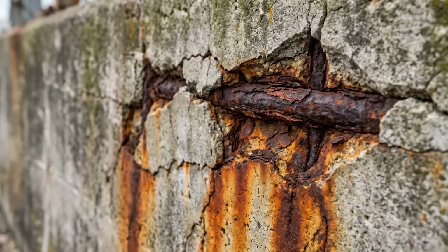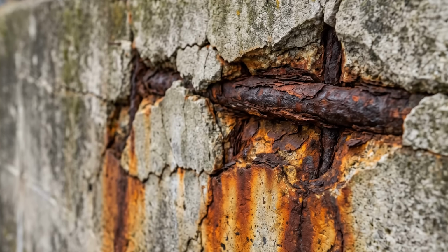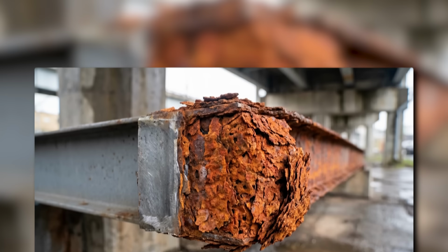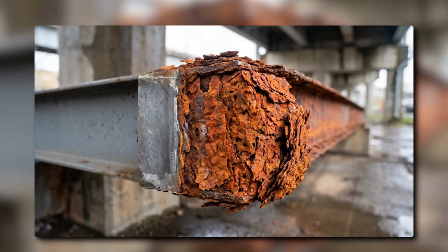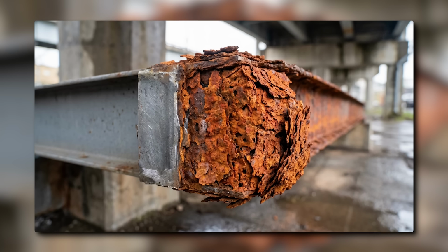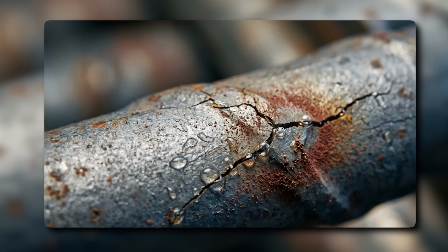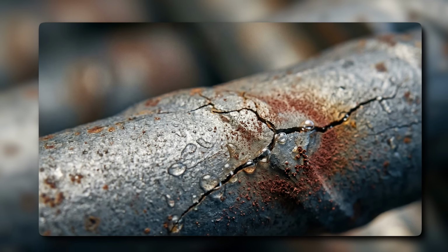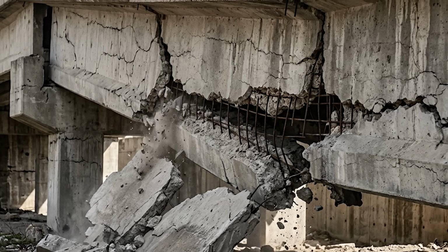Steel rebar has one fatal property: it rusts. The rust occupies up to 7 times the volume of the original steel. That is not a typo, by the way. When water and oxygen reach the bar through hairline cracks, the bar swells, the concrete cracks open further, and the structure fails.